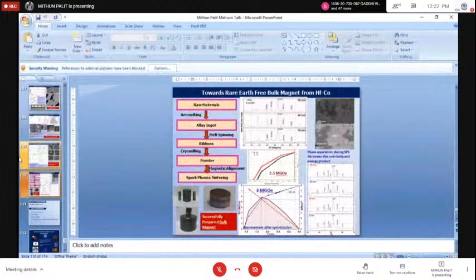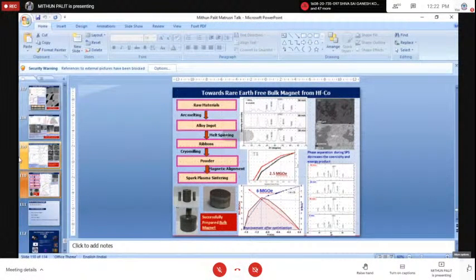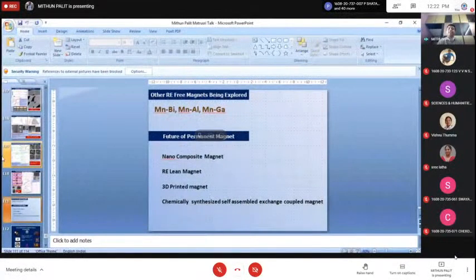We are nowhere when we compare with the rare earth permanent magnets. In rare earth permanent magnets we have 30 megagauss Oersted energy product for Sm2Co17. NdFeB has gone up to 50 plus megagauss Oersted energy product. So we are nowhere there, but theoretically all of them have potential, because they have been evaluated and it was found that both systems have the potential to deliver up to 35 megagauss Oersted energy product magnets. However, it is up to us how to do process engineering and microstructural engineering to realize a good magnet out of this system.